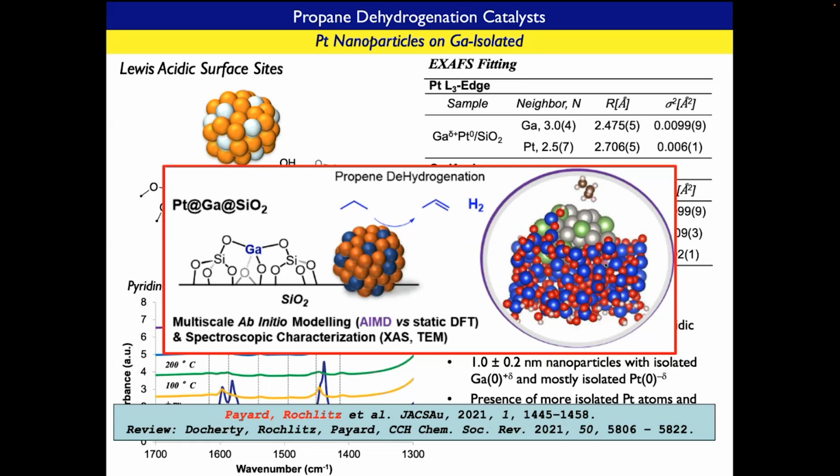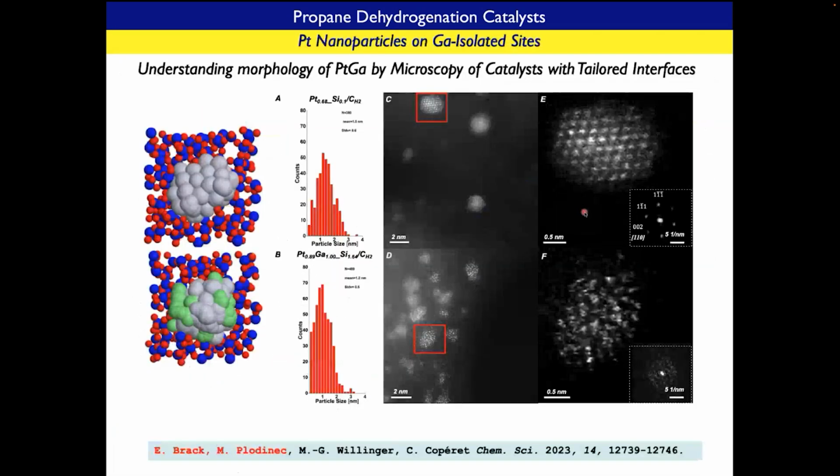So in that way, what you end up having is actually some isolated platinum atoms which are basically dispersed in some kind of gallium 0 sites. And with that, we could actually also show that in contrast to platinum, which remains crystalline, this is a case of platinum on silica, even though it's very, very small. When you go to actually platinum gallium, I showed by this metadynamic calculation, you can show that the system is much more dynamic and mobile.